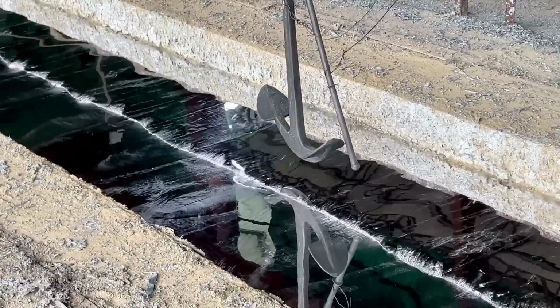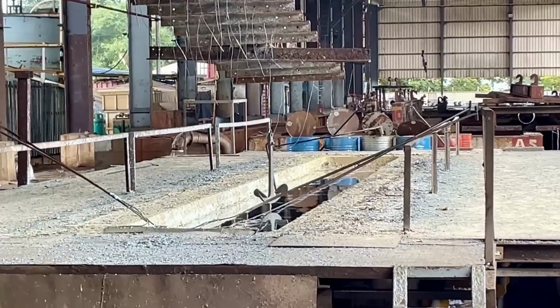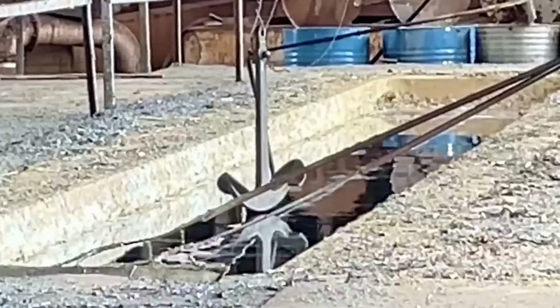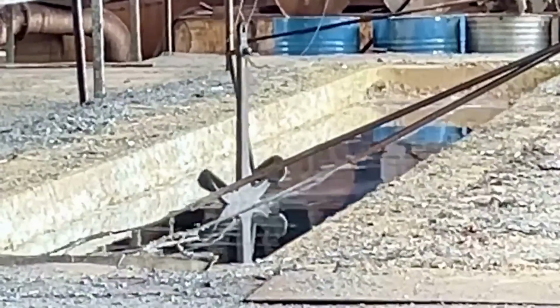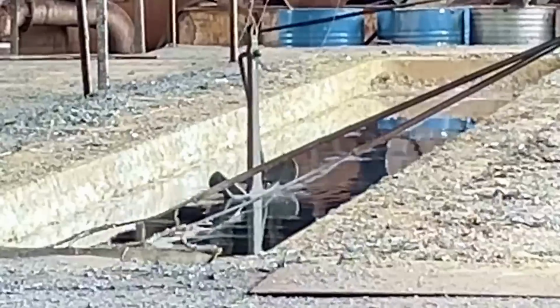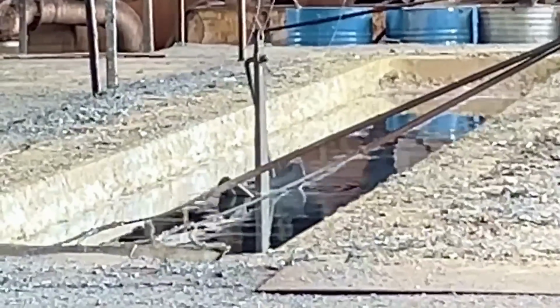The chain is then dipped into a bath of molten zinc. It remains in this bath for a few minutes, allowing the zinc to bond with the steel or iron at the molecular level, forming a zinc-iron alloy coating.